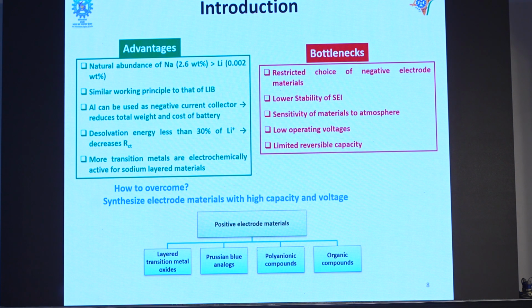An ideal solid electrolyte interface should be very uniform. It should be permeable to lithium transportation, and it should be stable. It shouldn't crack while you charge and discharge your electrodes. So lower stability of the SEI is one of the problems that sodium ion batteries are suffering from.